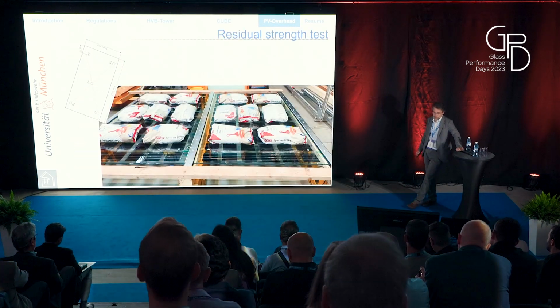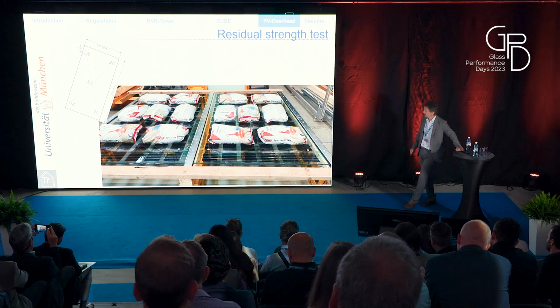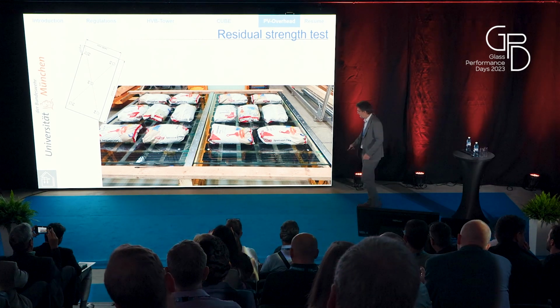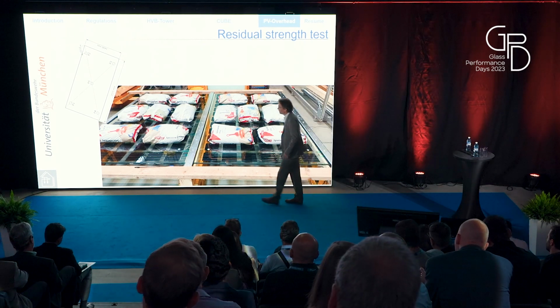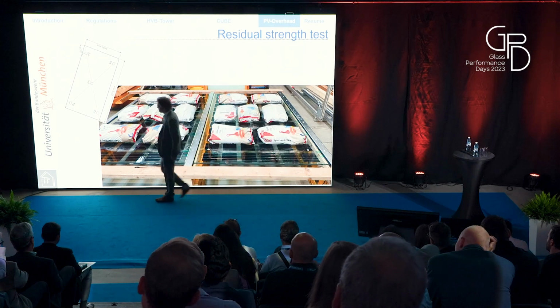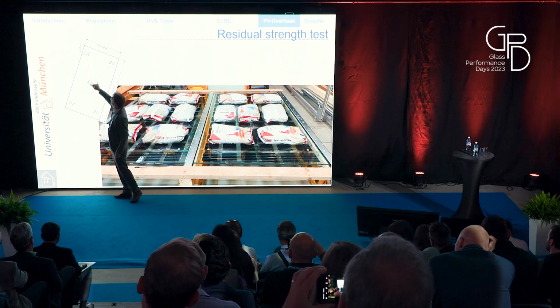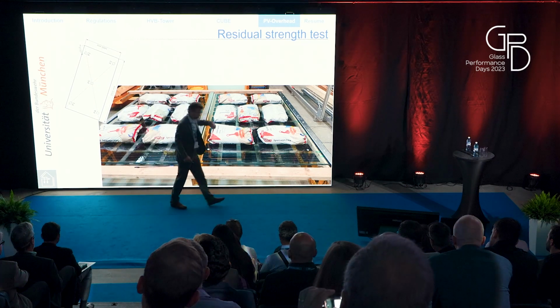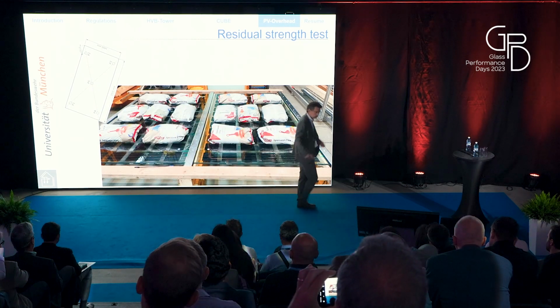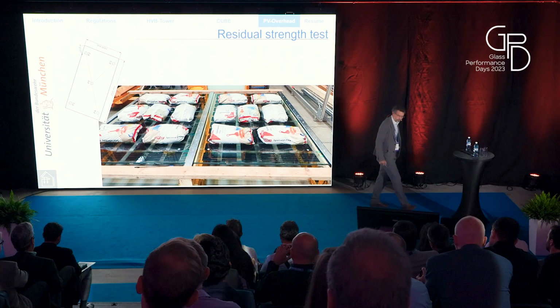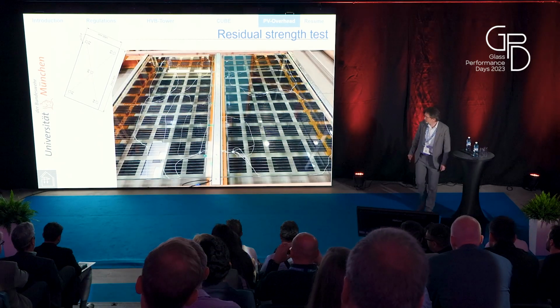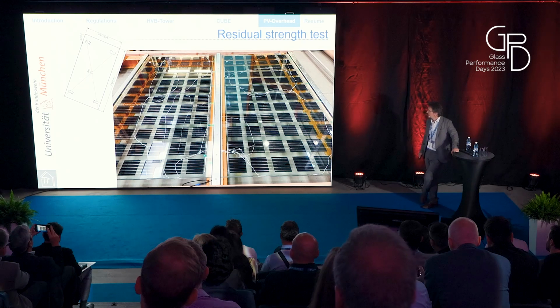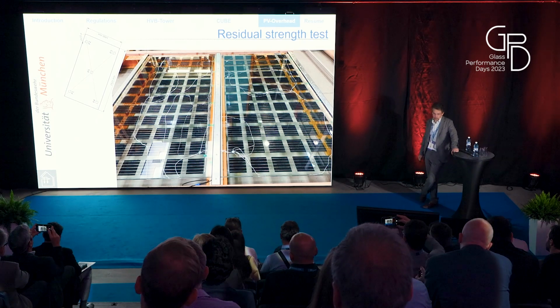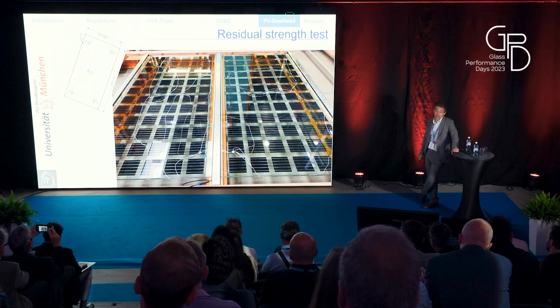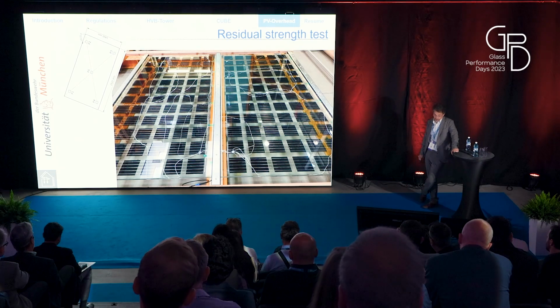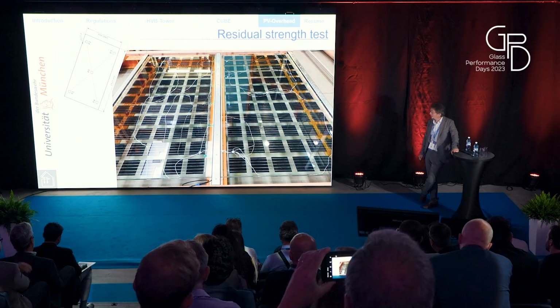We again had to do residual strength tests according to DIN 18008. We hit the glass at 5 points, near the corners and in the middle, on both sides, top and bottom, under load, and observe what happens for 24 hours. This is the breakage pattern after cleaning up. You see heat-strengthened glass performed very well. And when we get samples in our laboratory, well, this is not really broken.